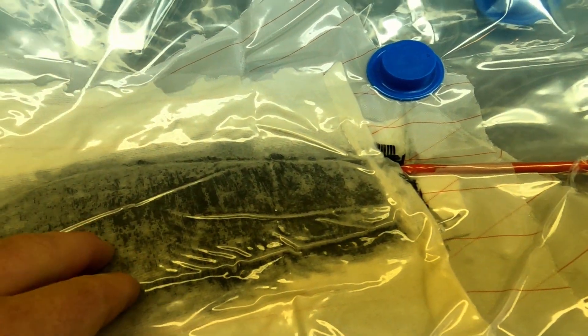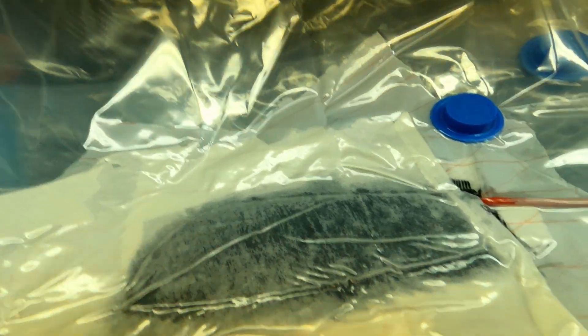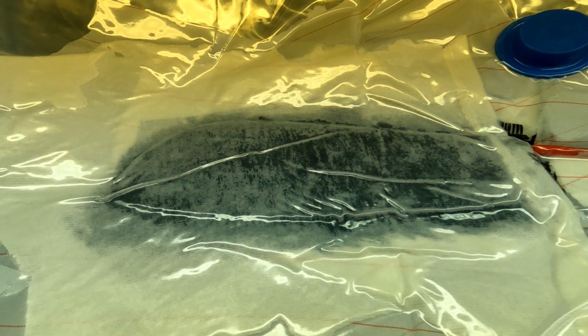I've never had a rudder break so this seems to work. It's PLA and the adhesion to PLA is not very good, but if you sand it good and clean it — I use some alcohol — and then one layer of 200 gram carbon on each side, it works pretty good. We'll see tomorrow how it looks.